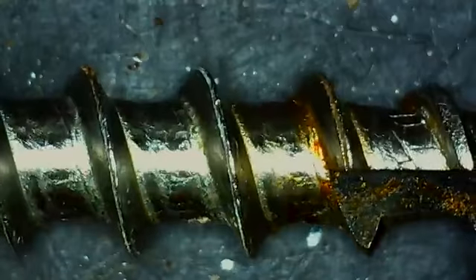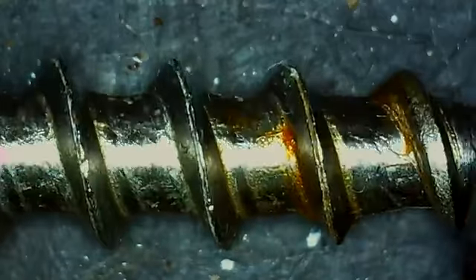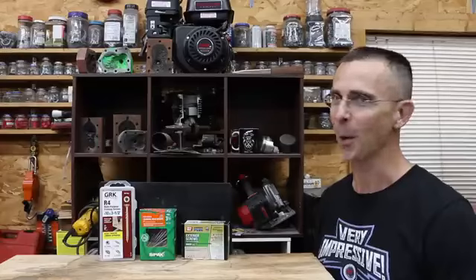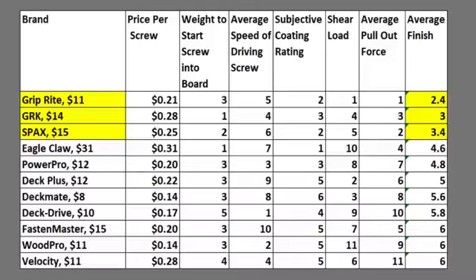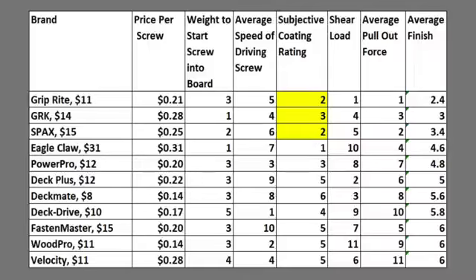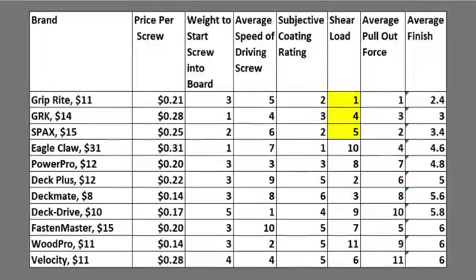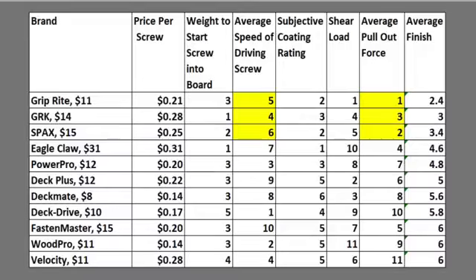I went ahead and tested the second screw using just the rusting agent, and it experienced very little corrosion. So which brand is best? I like the Grip Rite. It came in on top with an average finish of 2.4, but I also like the GRK and SPAX. The coatings of those brands were terrific, and all three had a top 5 finish for shear load. Not surprisingly, those 3 brands took longer to install, but the payoff is you get a screw that offers more holding strength.